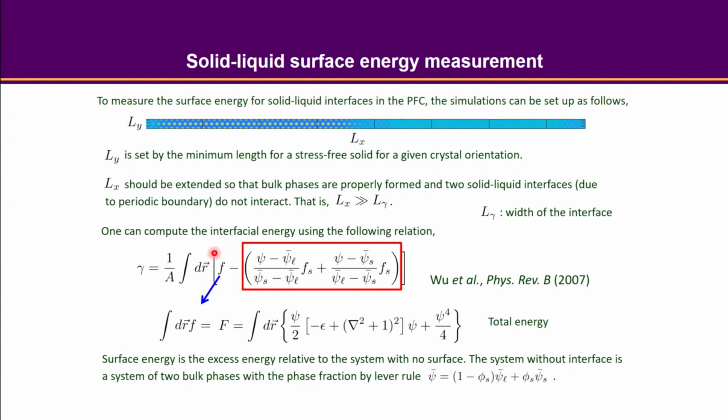But as you can see, if you carry out that spatial integral, what is the integral of psi over space? Because all others, they are just numbers. So here, basically, what you are having is just the mean density, right? So although I'm writing in this way, actually it doesn't depend on the detail of psi, how it distributes in space. Once you know the mean density, you know this term, what's the reference energy you should subtract off.